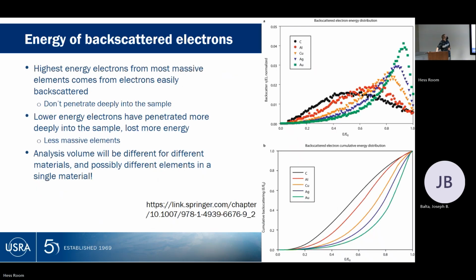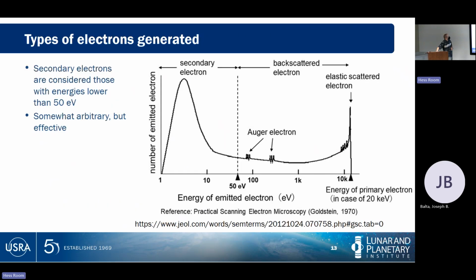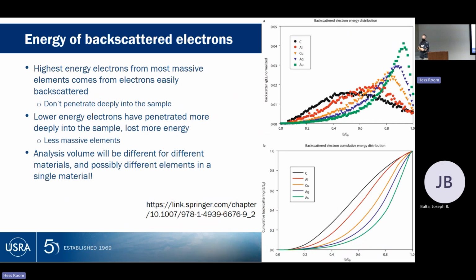Those are things, actually, you know what, I do want to mention a couple. Okay, yeah, we want to do this first. While we're talking about backscattered electrons, the most massive elements do the most easy job of backscattering. Okay? This is a plot of backscattered electrons normalized to total electrons and a plot of energy. So what do we see here? We have 5 elements: carbon, aluminum, copper, silver, and gold. With gold in the green, we have the highest yield of backscattered electrons and the highest fraction of the input energy comes back as backscattered electrons. In other words, gold or high mass elements are very efficient at producing backscattered electrons.